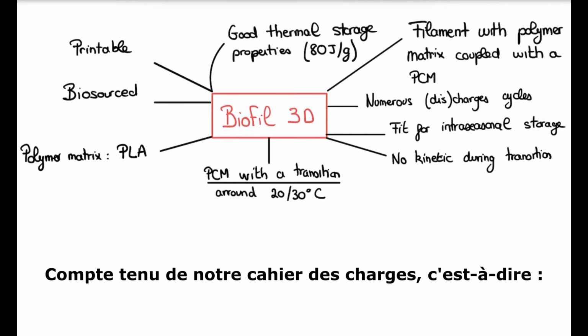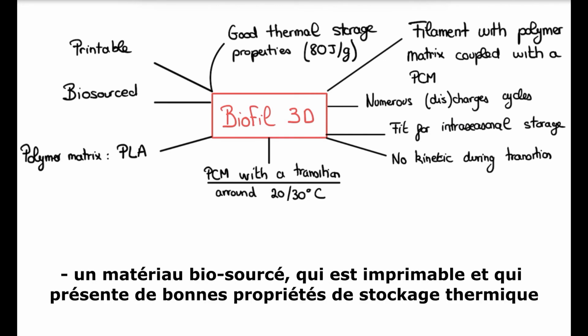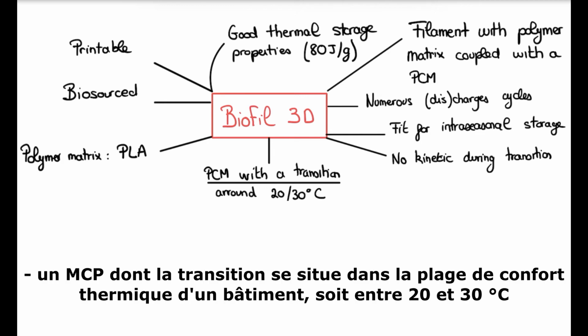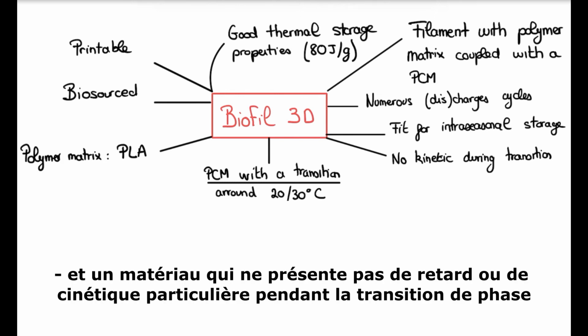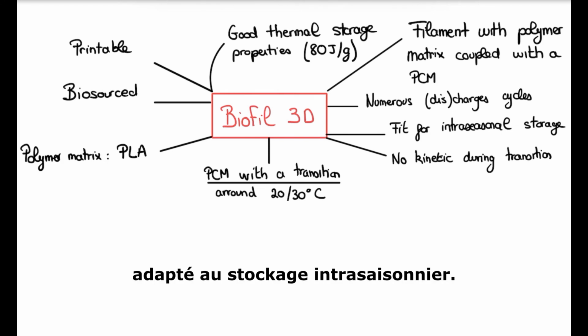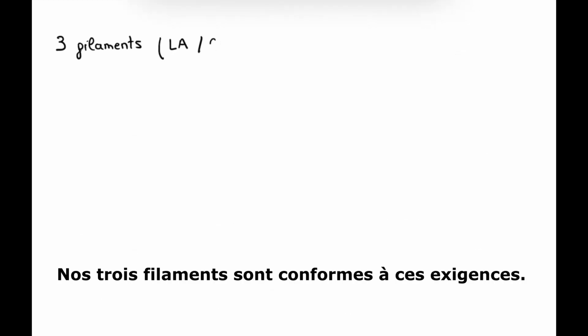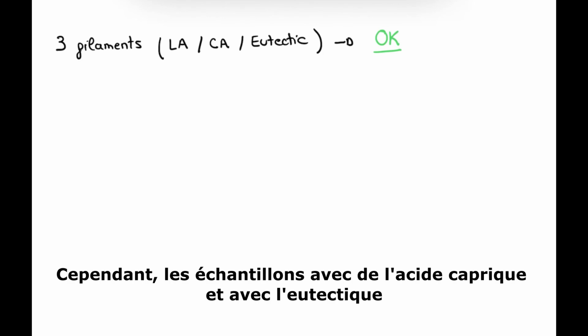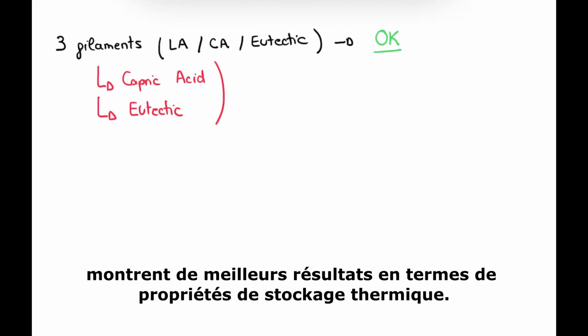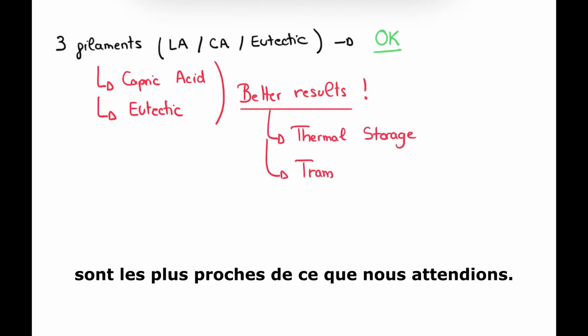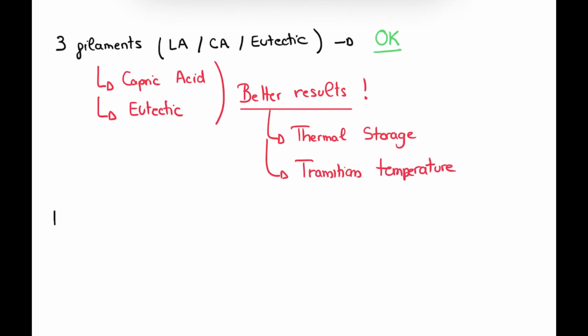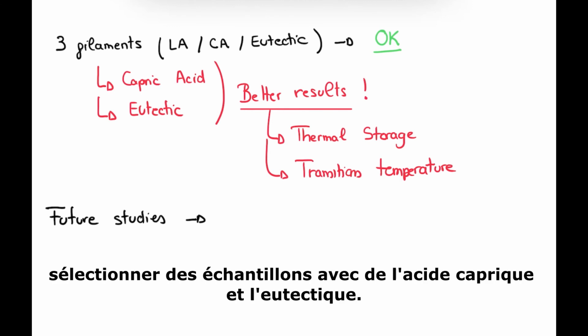Considering our specifications, that is to say, a biosourced material that is printable and with good thermal storage properties, a PCM that shows a transition within the thermal comfort range in a building around 20 to 30 degrees, and a material that shows no delay or particular kinetics during the phase transition, fit for intra-seasonal storage. Our three filaments are in line with these requirements. However, the samples with capric acid and with the eutectic show better results in terms of thermal storage properties. Additionally, the transition temperatures are the closest match to what we were expecting. Consequently, our recommendations for future studies are to select samples with capric acid and the eutectic.